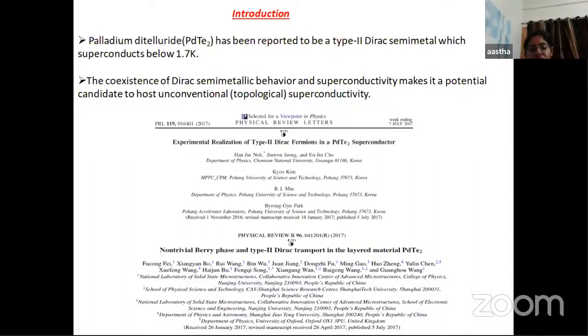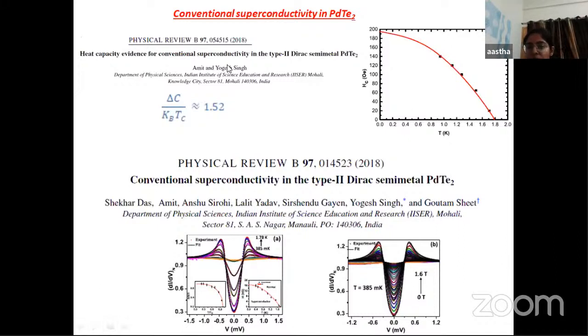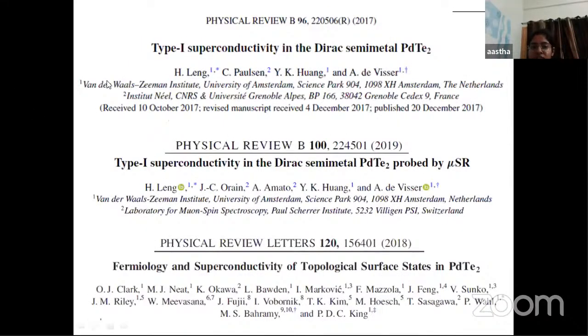However, despite the speculations on the possibility of a type 2 Dirac semimetallic phase or unconventional superconductivity in PdTe2, the STM as well as heat capacity measurements showed that the superconducting phase in PdTe2 is rather conventional in nature. As far as its magnetic properties are concerned, this superconducting phase remained indeed interesting, because this group initially showed type 1 superconductivity in PdTe2 by magnetization as well as transport measurements, and later they showed the same type 1 superconductivity by μSR experiment.